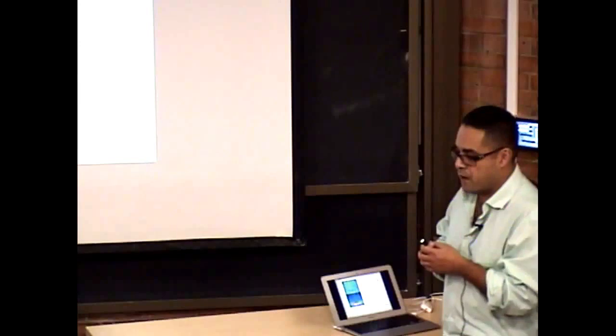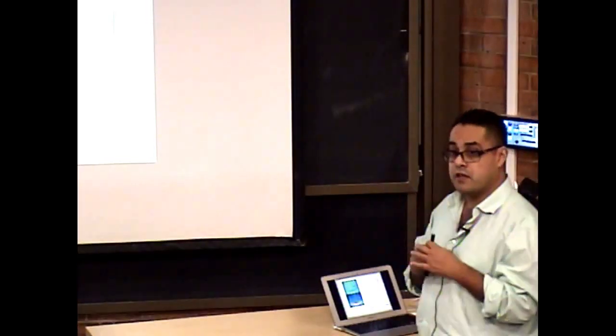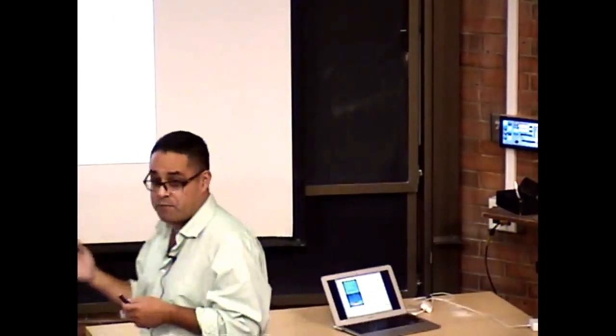You're coupling in a strong way the exciton and the photon that is strongly confined in the microcavity, and you make what you call cavity polaritons, which depending on the design of the microcavity and the properties of the exciton, can be in a really significantly strong coupling limit, so that essentially in gallium arsenide you can show that at 4 Kelvin you can form something akin to a Bose-Einstein condensate. So this emergence of spontaneous coherence in gallium arsenide: can we do that not at 4 Kelvin, but at what I'd say is the minimum temperature that would be acceptable for an actual application, which would be Montreal in January? If it can work in Montreal in January, at least that's what we should be. That should be our minimum requirement.